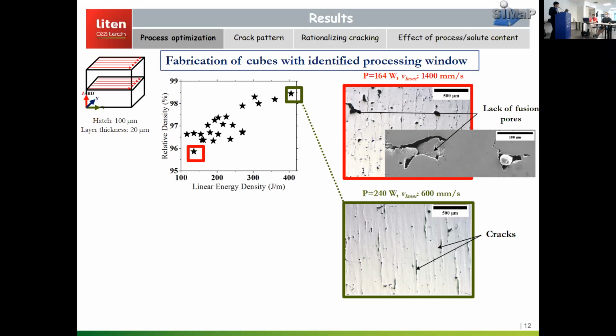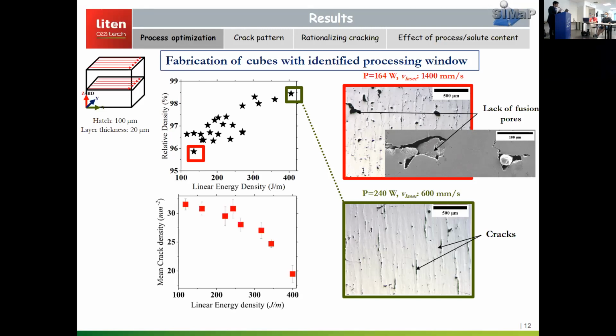We achieve good relative density up to 98.5%, but we still have cracks present in the microstructure. So all the stable conditions led to cracking. But there was a particular trend that we observed in the cracking. The mean cracking density measured from the microstructure decreased as a function of linear energy density. So now one can say that since we give increasing linear energy density, you can decrease the cracking tendency.